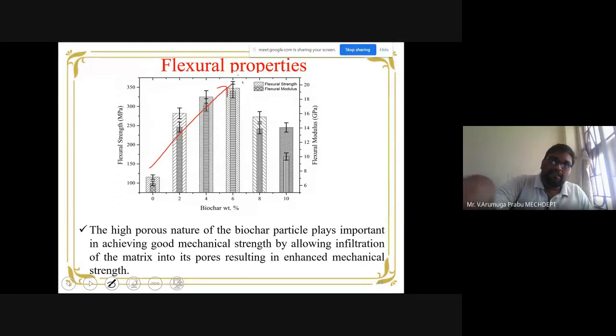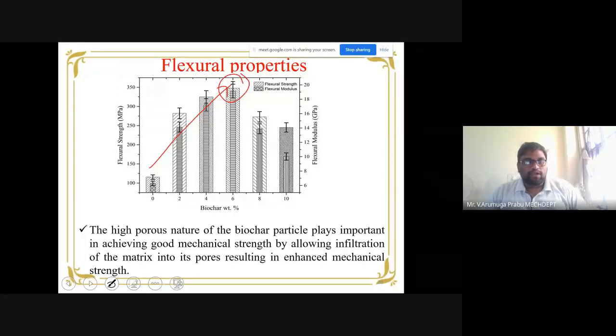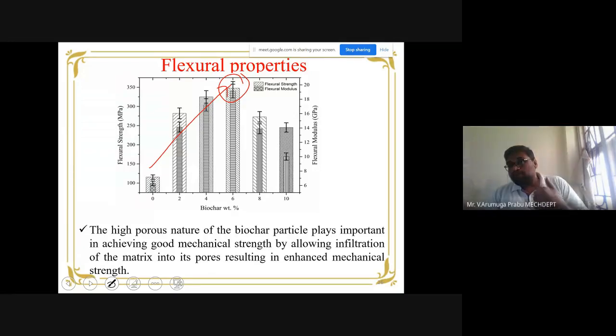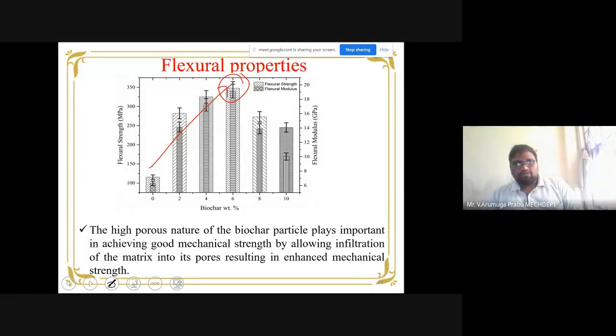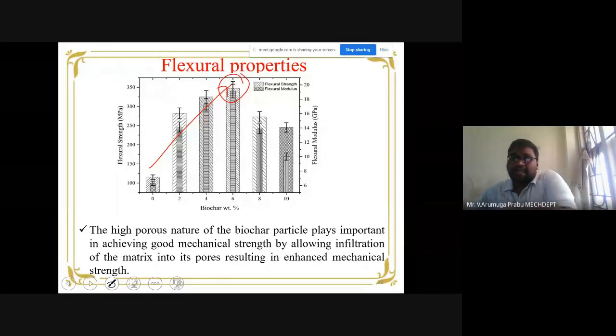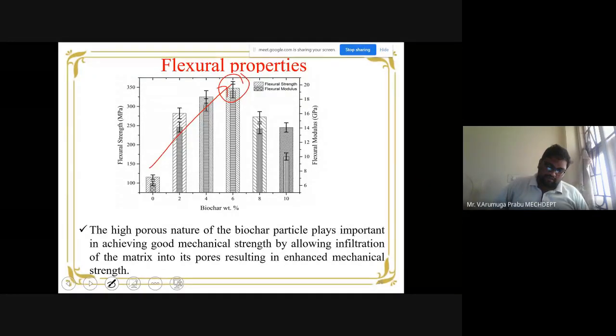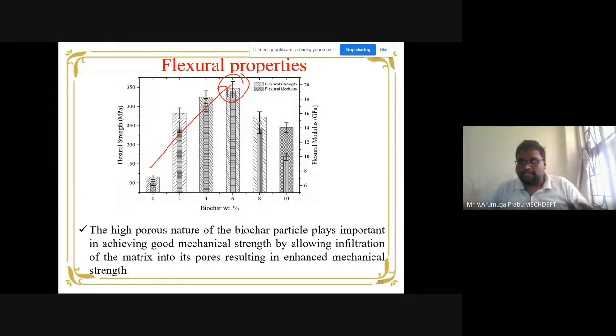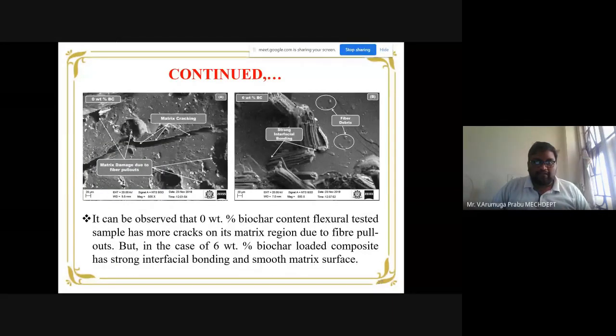See the increase again at the 6 weight percentage addition of biochar. Why is good mechanical strength obtained? Because of the high porous nature of the biochar. That's another important speciality of your biochar, which plays a vital role in achieving good mechanical strength, in such a way that we are able to attain enhanced mechanical strength in all the cases. That's the one thing I would like to highlight, regarding your flexural properties.